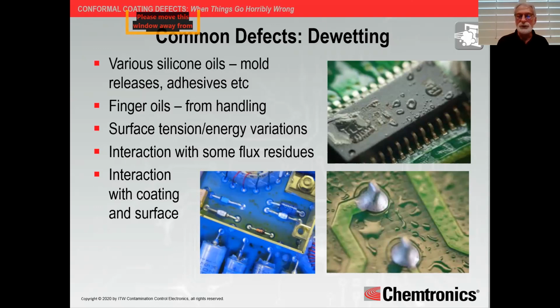You can have some interaction with flux residues because of the binders, the rheology modifiers, the ingredients, let's say, that's left over after the soldering process. These residues sometimes do not allow proper wetting of the coating. And again, interaction with the coating and the surface. It's because there are just differences between the surface tension of the liquid and the surface energy of the surface, whether it's a component casing, whether it's a board laminate. You see this in the bottom right-hand picture, that obviously that coating is not leveled out and adhering and wetting that entire surface.